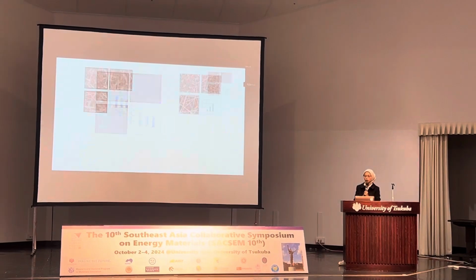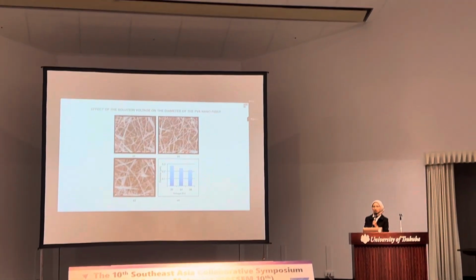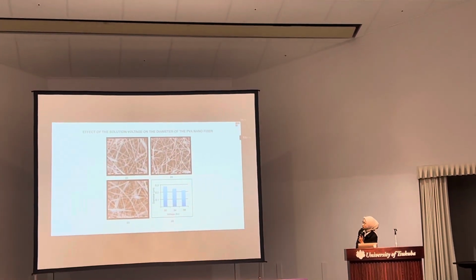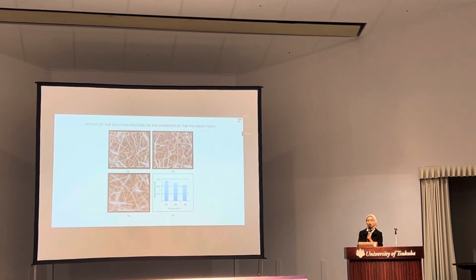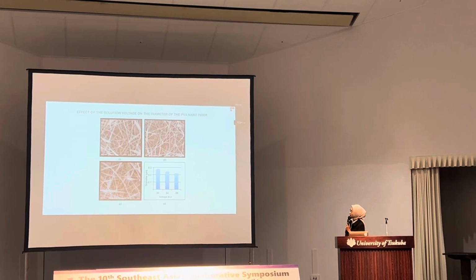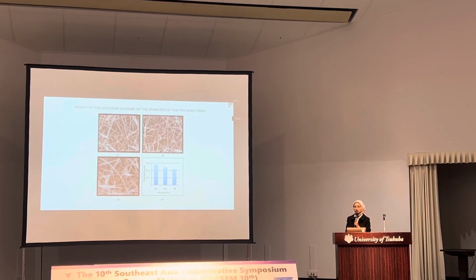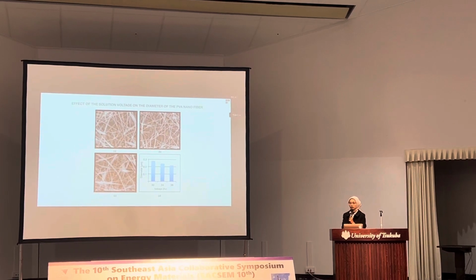Two, the reason why when the voltage is increased, the diameter decreases, is because when the voltage is higher, the solution droplet volume at the end of the tip is smaller. The smaller the droplet, the thinner the diameter of the nanofiber.